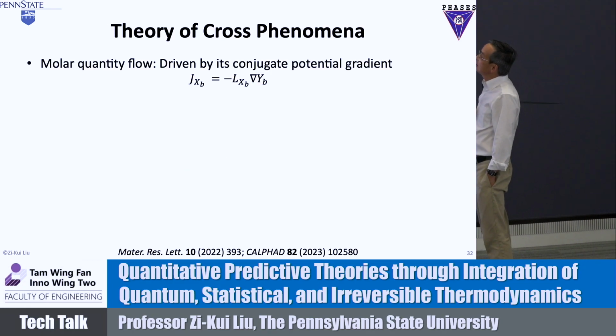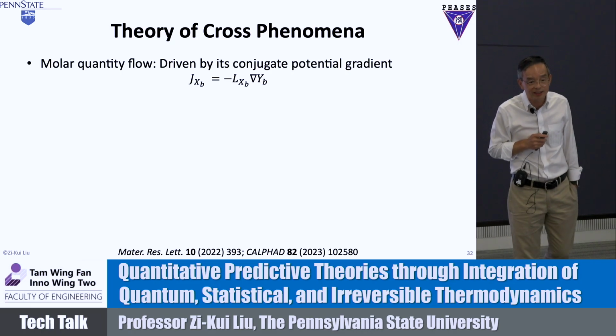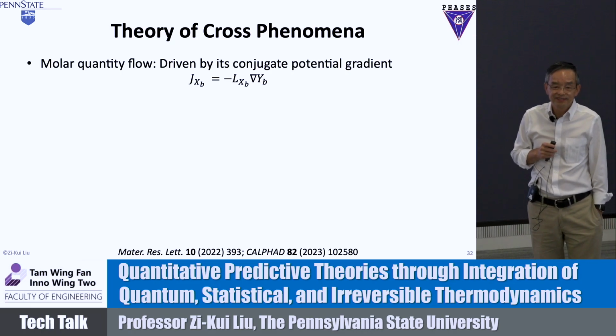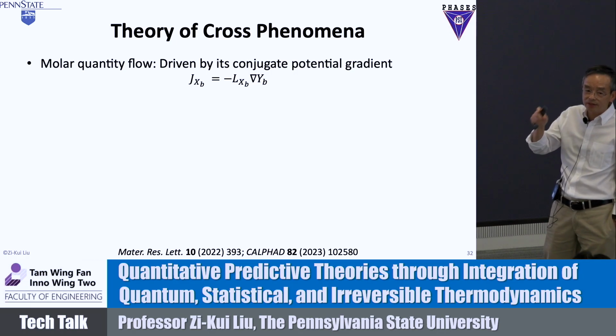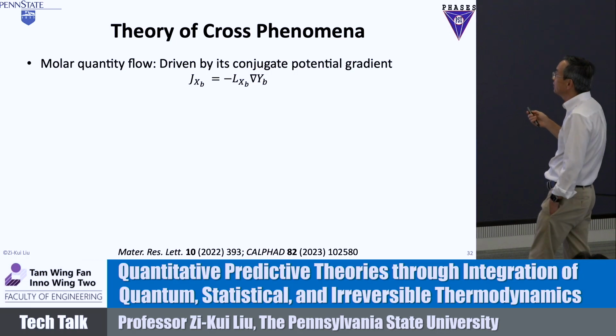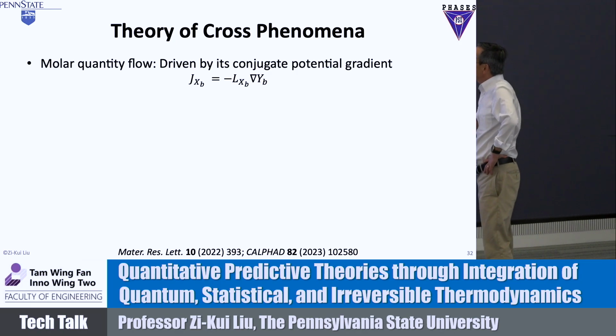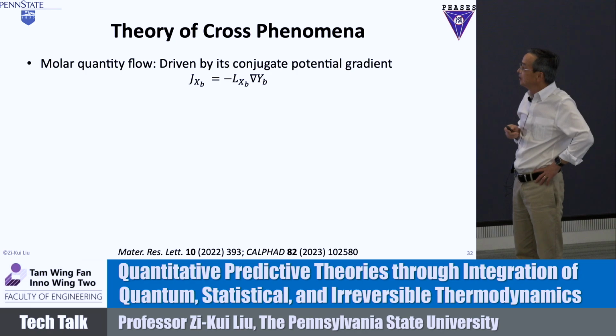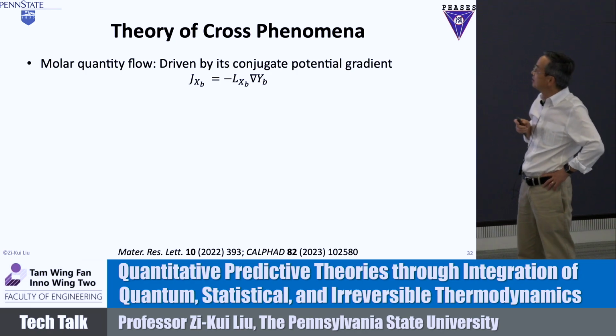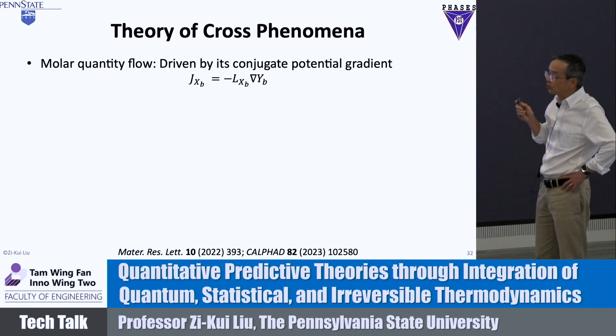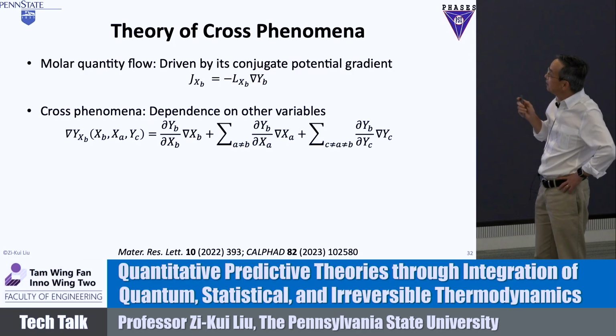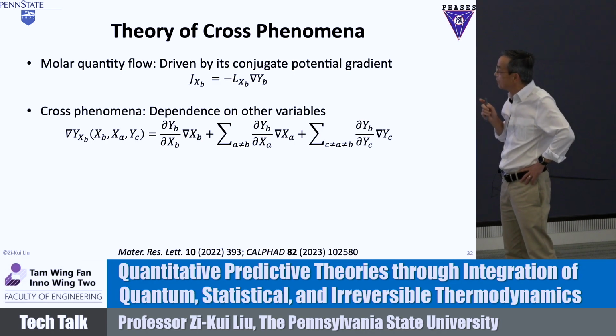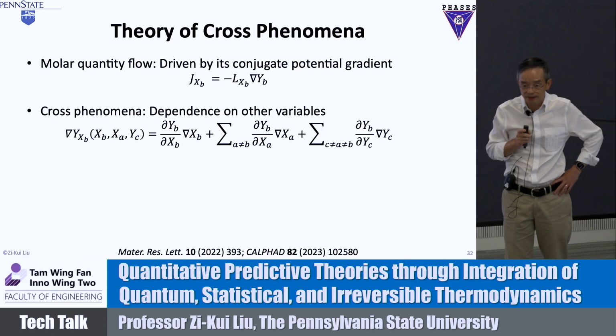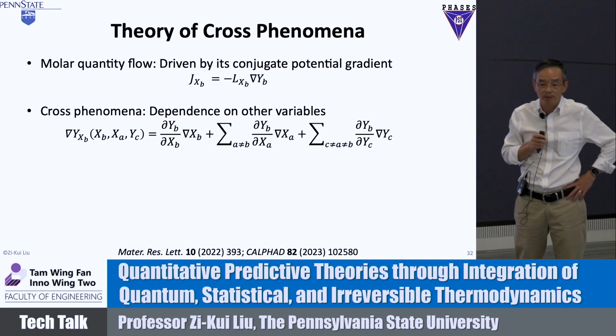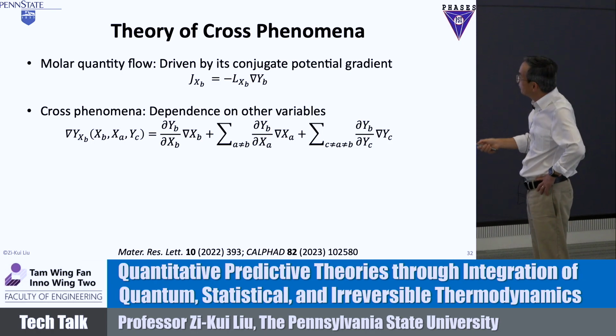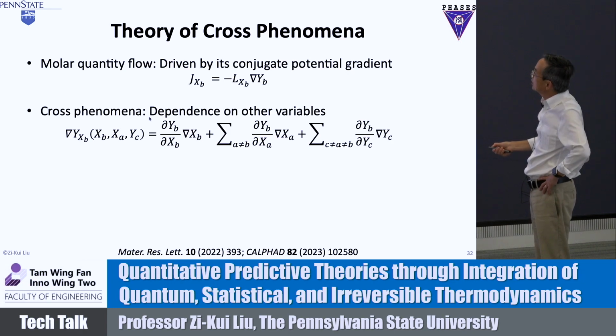All right, so what it means is that we still have to explain how heat drives diffusion, right? How does the temperature gradient drive electron motion? Or diffusion in general, thermal diffusion. So this is our general equation. The flux of a molar quantity is only proportional to its own conjugated potential gradient with a coefficient. That's a true kinetic coefficient. However, that potential gradient is a function of all variables you can control in the system. So that's where the cross phenomena come in. That means the first term you have here will be the conjugated variable, right?